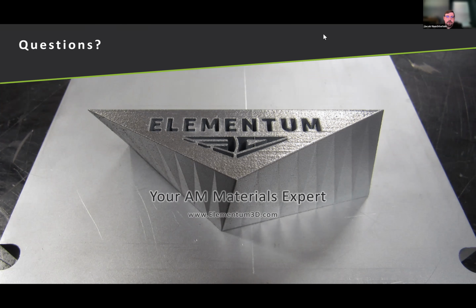Yeah, so the first question here that I want to talk about is the burn off of a coating. So the coating isn't a polymer based coating; it's an oxide based coating. So I don't think that there's any difficulties there of having problems with the burn off. Essentially, you might get some vaporization of it, but then it's pulled away by the vapor pull. So when we're measuring thermal conductivity or looking at it under SEM, there's no residual coating. That coating is super thin.